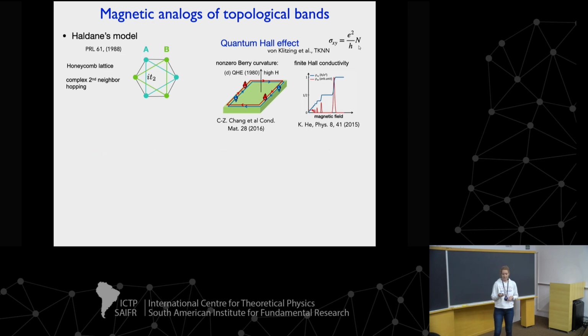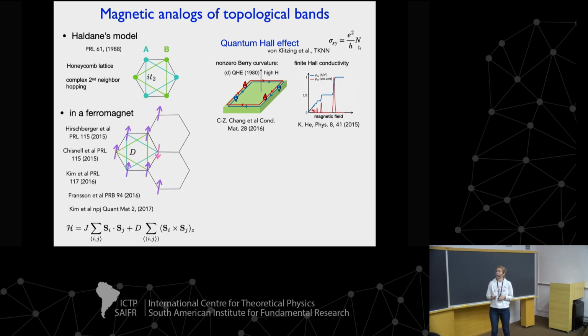What we are interested in is when this happens in magnets, in fact, in the excitations of different magnetic systems. For example, if we take a simple ferromagnet that is topologically trivial, and we think about the magnetic excitations of this system, which correspond to a spin flip, that can propagate over the lattice and form bands very similar to electrons, then we can ask the same questions as we would for the bands of electrons, like what is the topology of these bands.